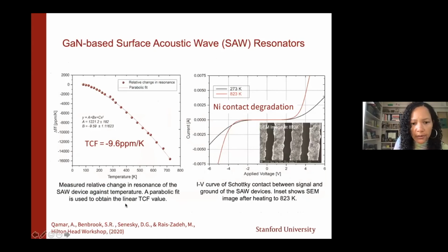So what we're gearing up to do and what we've been doing, I don't show all the data here, but happy to share with anybody who's interested. We've looked at carbon doping and silicon doping and the influence of the gallium nitride doping on the temperature coefficient of frequency. And then we're also gearing up to do temperature compensation. The turnover temperatures are at low temperature for our current architecture, but introducing materials such as silicon dioxide with a positive temperature coefficient of elasticity, where the material stiffens as you increase the temperature, we can start to counteract and tweak the turnover temperatures. We're also translating our first generation of device. We used a nickel contact, which was degrading, so we're having a Schottky response, and then we're going to be transitioning to our high temperature metals.